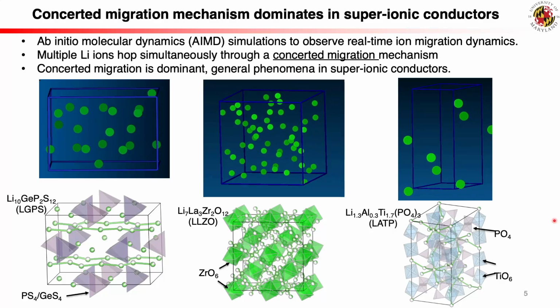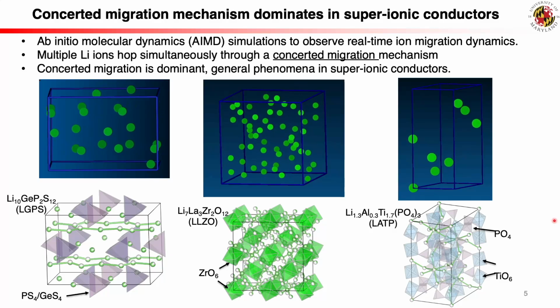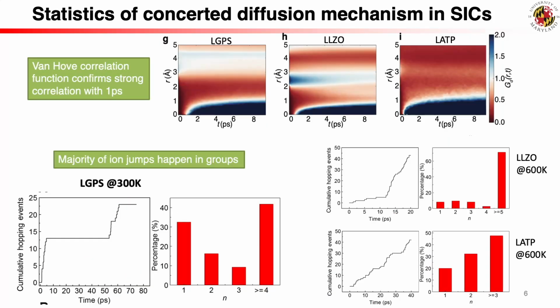They also looked at Van Hove correlation functions. They show you how the movement of one ion influences its neighbors over time, a measure of the correlation. Those functions clearly showed these correlated movements, which you can see in figure 2 of the paper. To quantify this, they calculated correlation factors, which are related to the Haven ratio.